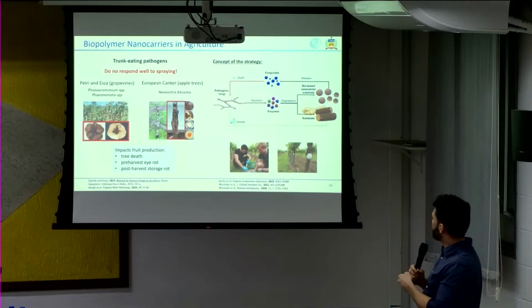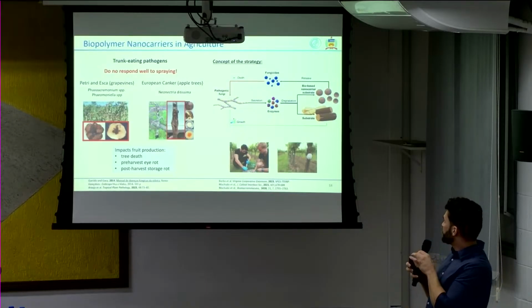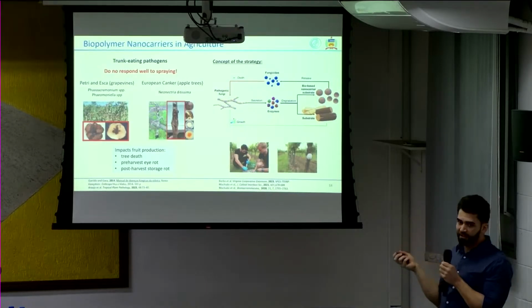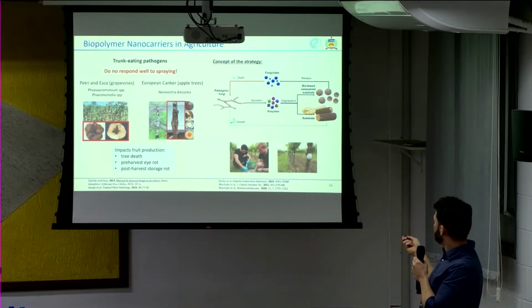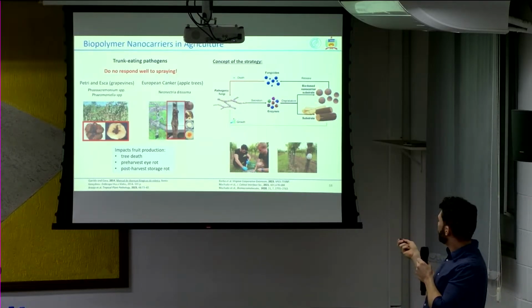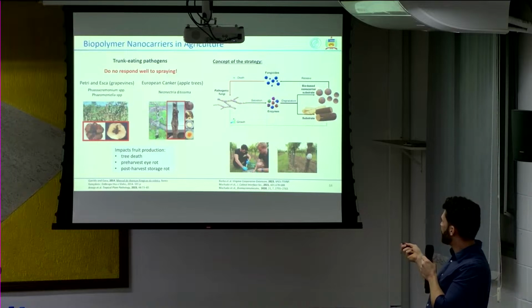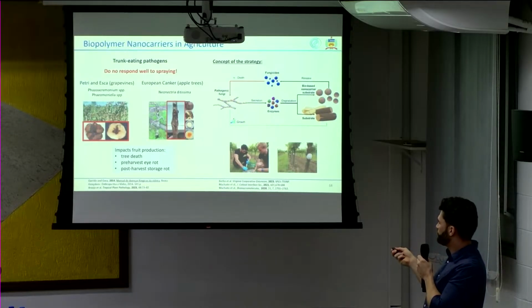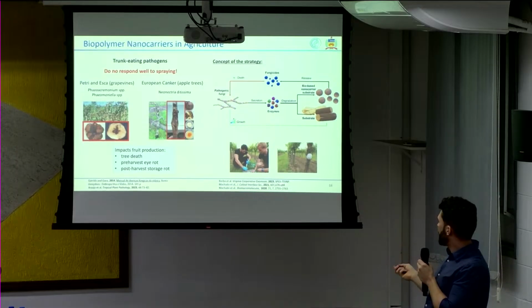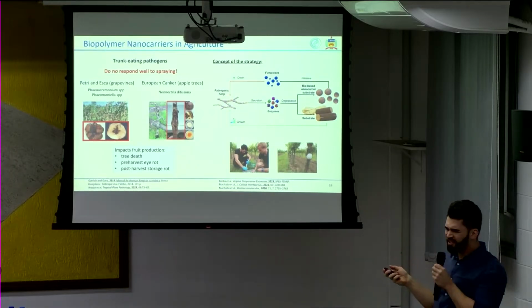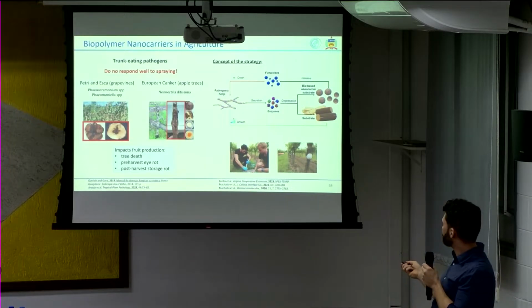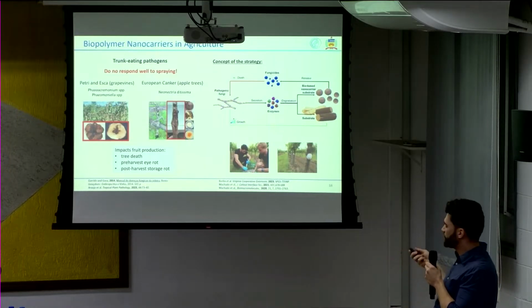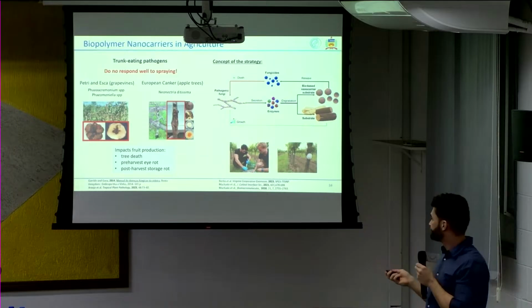So the concept of this strategy was to use the same substrate, so in this case, lignin and cellulose, to compose the nanocarriers. So when the fungi release the enzymes, instead of degrading the substrate, they degrade the nanocarriers that are loaded with fungicides, and then the fungicides are released in loci, and the fungi dies. And we even did some studies in the field injecting latexes or nanoparticle dispersions in the trees.